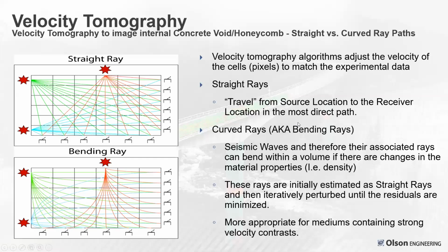So just taking a measurement over 4.5 feet, you need to think of that as an average velocity, because it is. It's just the time required. So with tomography, and by doing angled testing where you have crossing ray paths on a grid, then you can determine which of these pixels, if you want to think of it that way, in a cross-sectional sense, say this was a beam or a column, that by having crossing ray paths, you can mathematically in the algorithms adjust the velocity of the pixels to match the experimental data.